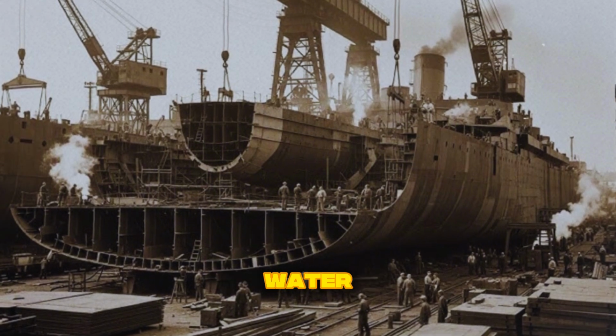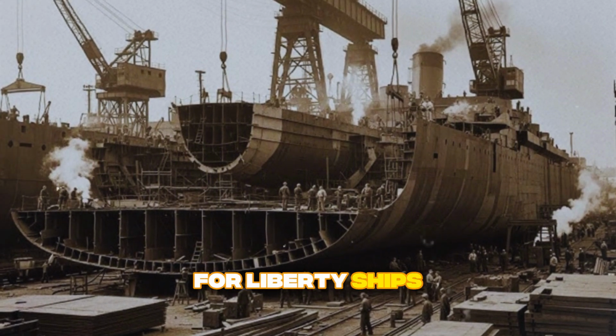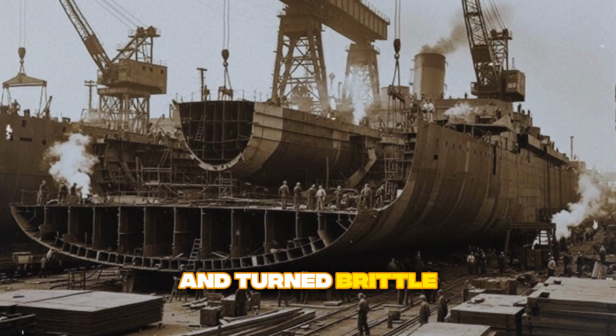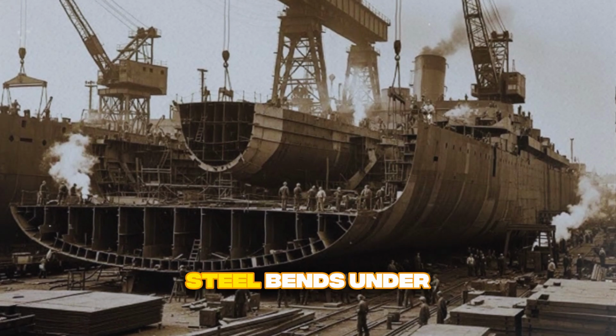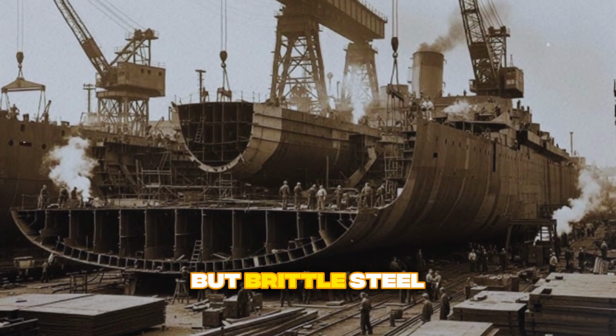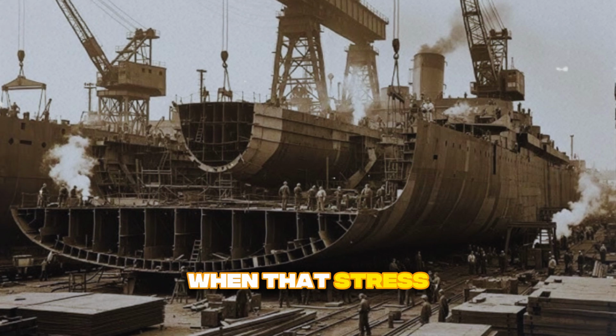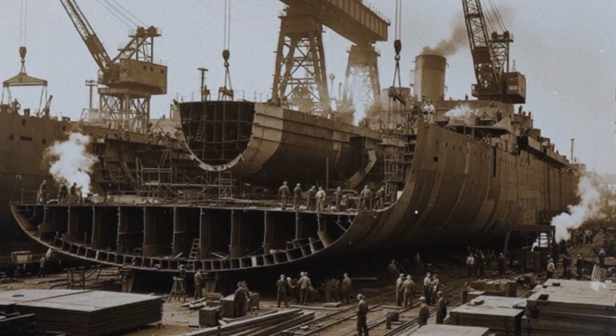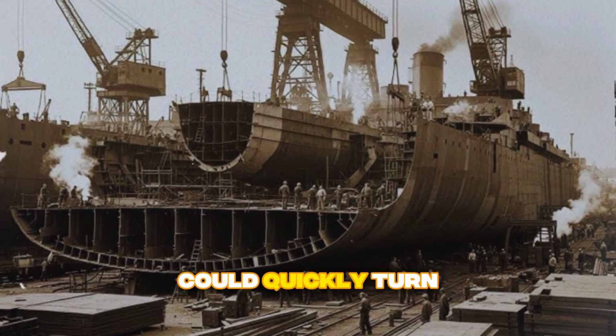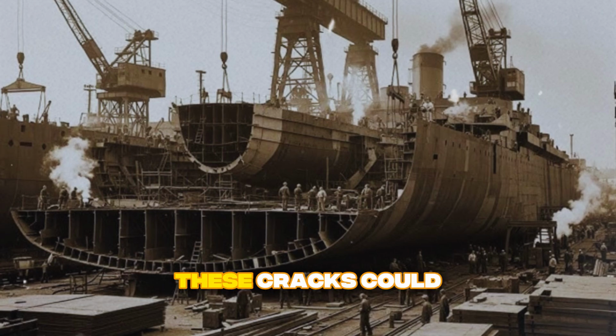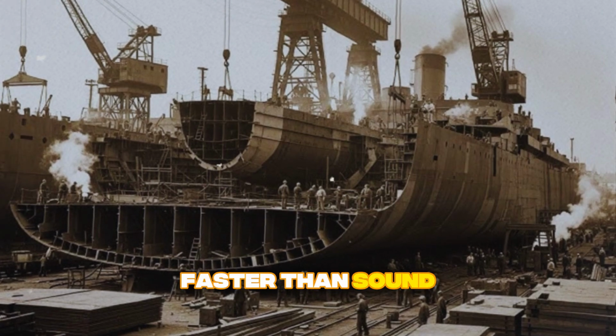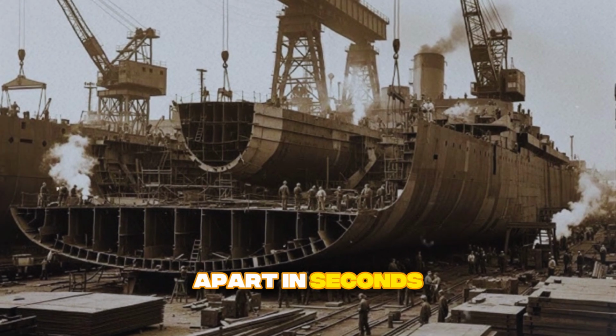In cold water, the steel used for Liberty ships lost its flexibility and turned brittle. Normally, steel bends under pressure, but brittle steel breaks. When that stress met a sharp corner, like a hatch, even a small crack could quickly turn into a massive split. These cracks could move at speeds faster than sound, tearing the ship apart in seconds.